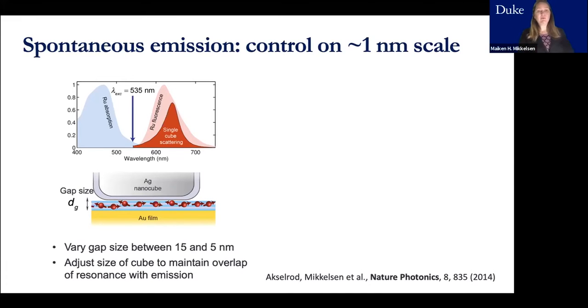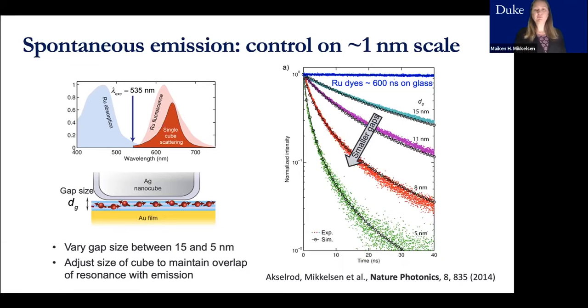To explore that, we decided to vary the gap size between 5 and 15 nanometers. While we are varying the gap size, naturally the plasmon resonance will change as well. To account for that, we modified the size of the cube such that we could constantly keep the plasmon resonance overlapping with the emission. The dark red here indicates the plasmon resonance, and the pink is the fluorescence. We want these two to overlap so that we are on resonance with the emission, which is what gives us the largest enhancement in the spontaneous emission rate.